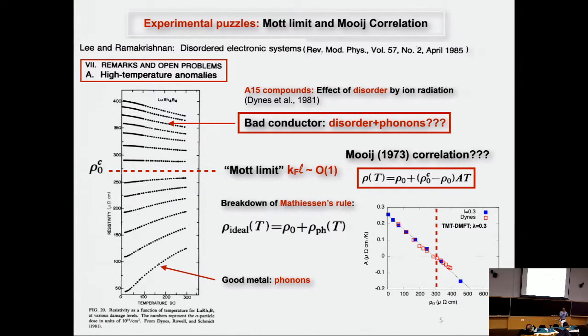Mott said that the mean free path, which is the main object in Drude theory, when it becomes comparable to the lattice spacing, then we cannot go further in the metal, and something has to happen. Mott suggested that the conductivity should drop to zero in a first order fashion. Later, when the scaling theory, localization, etc., came forward, it became clear this is not exactly correct, but this Mott limit served as a demarcation line between a good metal conductor with Drude transport and scattering picture and something else. And of course, at stronger disorder, you have an insulator, but all these curves here, as you can see, are not insulating. They have a negative slope, and they go to a finite value. If you go to stronger disorder, eventually you will get exponentially rising resistivity. But there is this intermediate regime which has been mysterious.